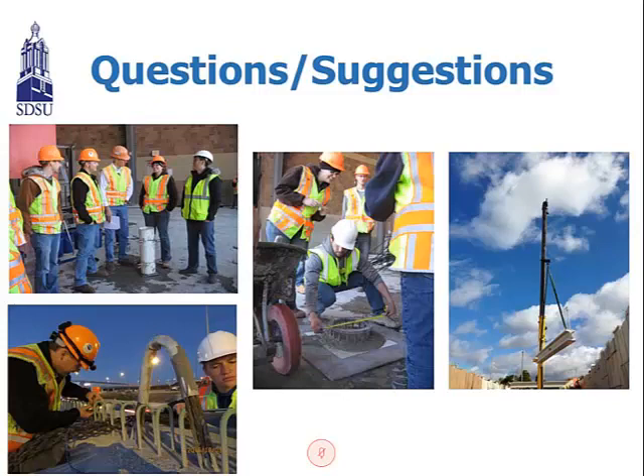Okay, that's good information. The camber, did you do multiple beams there? My memory of prestressed beams is that they vary quite a bit even when using conventional concrete. That was a very small camber variance, I would assume. Is that what you assume too? Yes, that's what we assume. That's why we compare the camber between the normal concrete and SCC girder. And you can see the conventional was less, and the SCC is a little bit higher, which is what you expect.